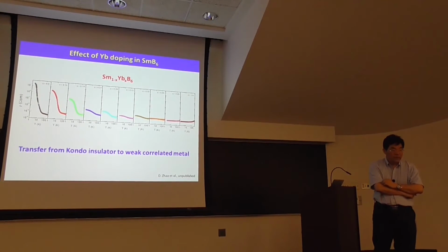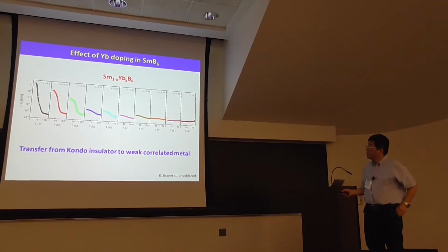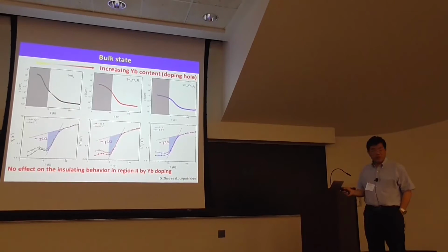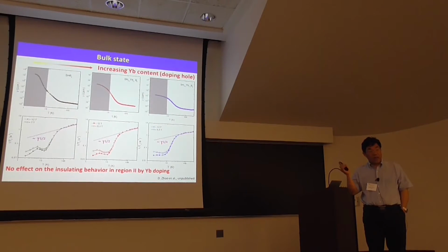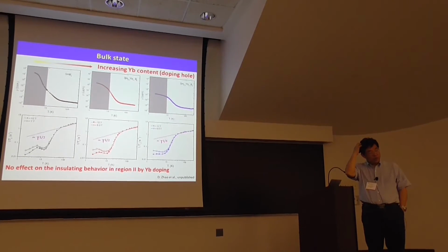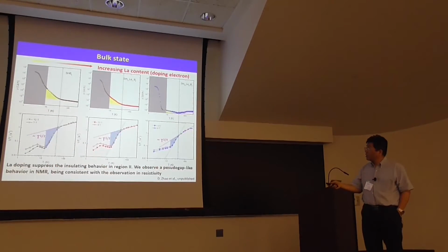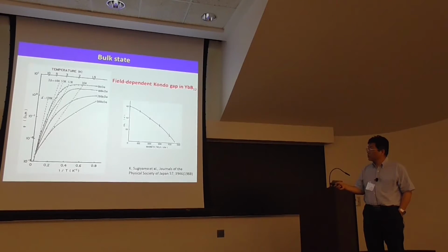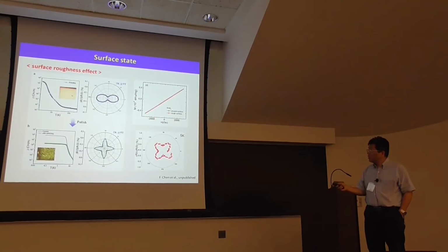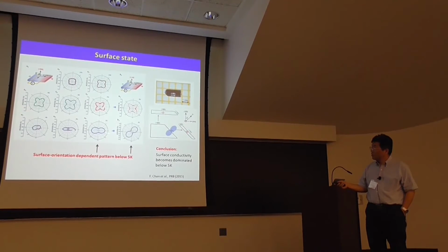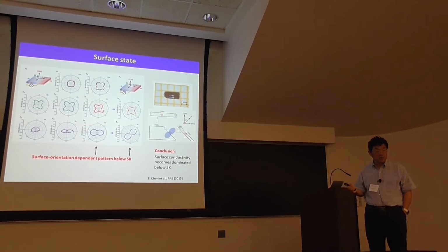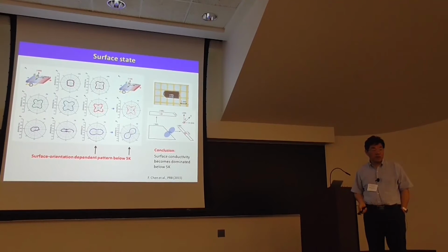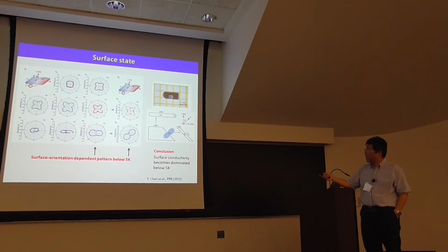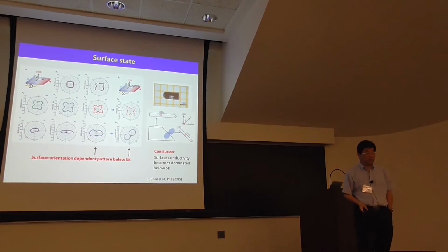Asking about the magnetoresistance of the bulk. We can do that, because for the bulk at high temperature, the magnetoresistance is very small, almost close to zero. I don't know why you want to know the bulk contribution. What about at low temperatures? For the low temperatures, you can't extract it. That's the surface. Yes, because just below 4-5 Kelvin it is the surface. Also, this magnetoresistance here is larger than this here.